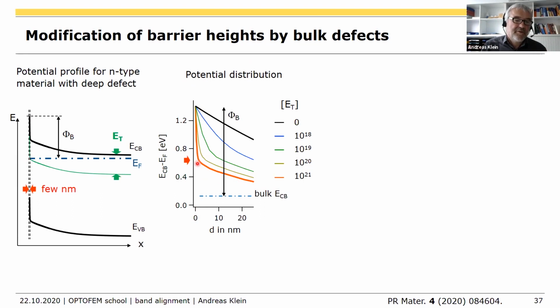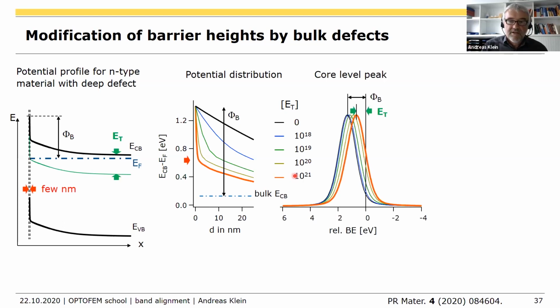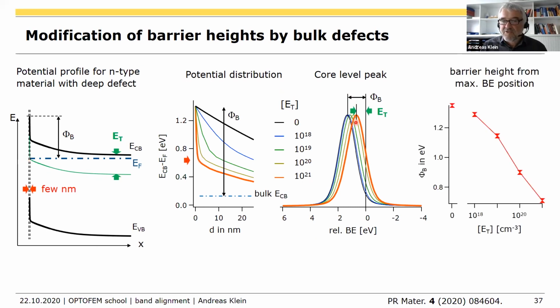And if it's even narrower, in principle, you measure the Fermi level position here and not here if you have a high defect concentration. So that's the simulation of the spectra, how they would look like. You could really see how much, this is the Schottky barrier, and you see how much the defect levels are changing. And ideally, this is a possibility to determine the trap energy, which would be here, or here. And that's just how to plot the barrier height as a function of trap.